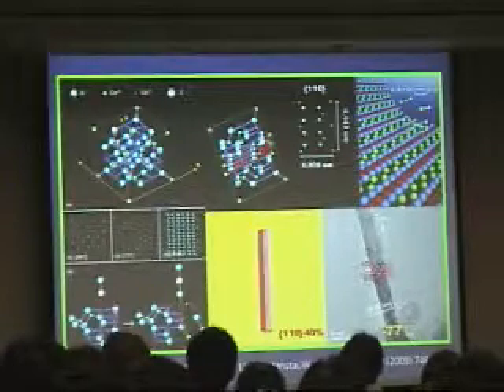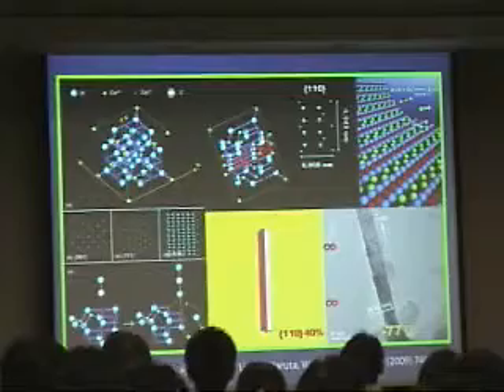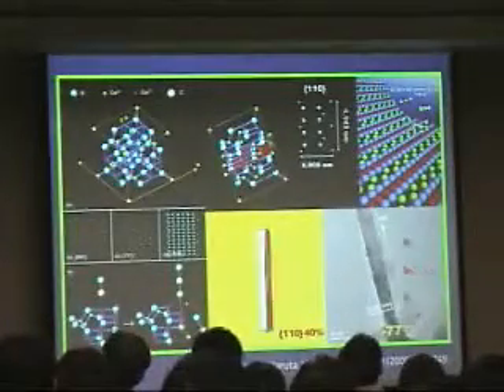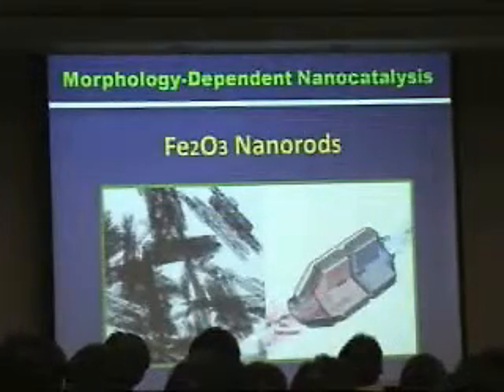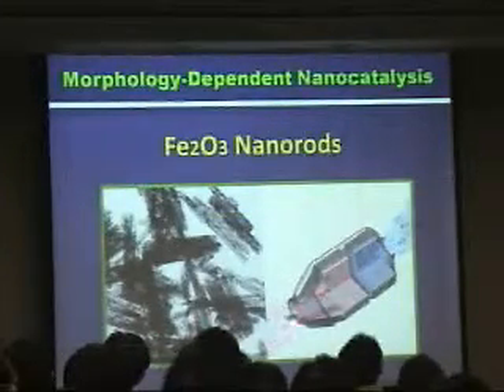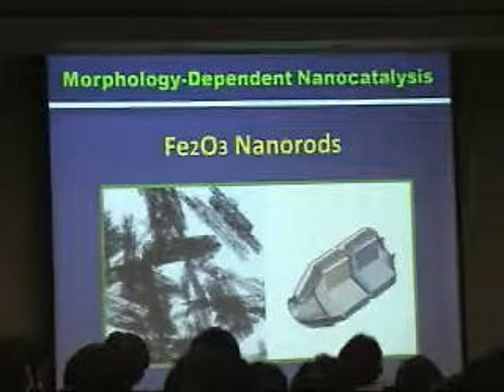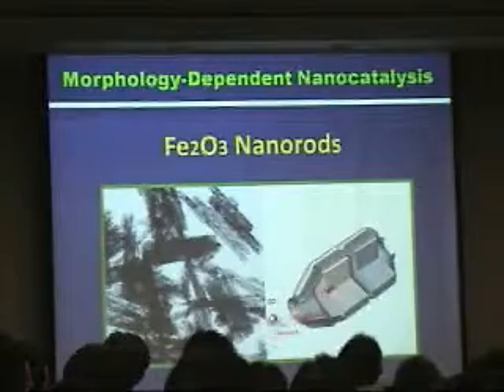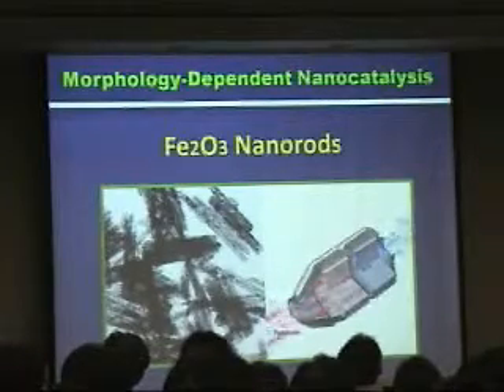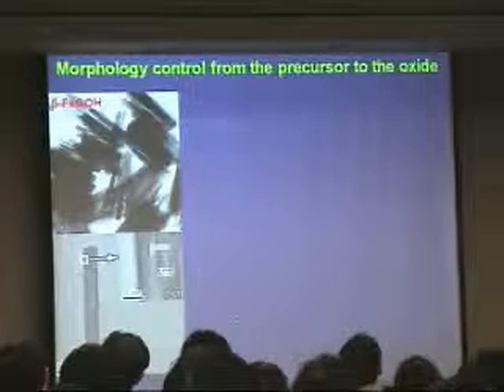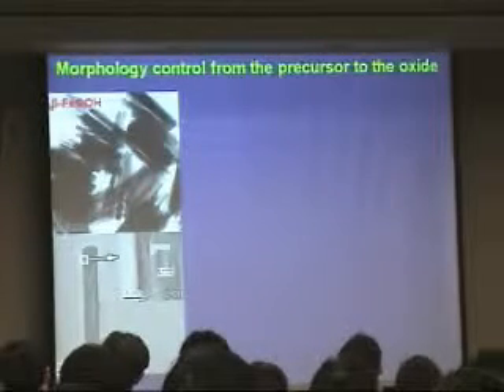So after this work, we also wanted to confirm the stability of this nanorod. We operated some other reaction at 500 degrees C. We still confirmed the stability of this nanorod and also the presence of the active site even after the reaction. Okay, so following this concept, we used another metal oxide, and we also got the same phenomena. That is the more common iron oxide nanorods. This oxide is very cheap and is also a very environmentally benign material. And we also started from the solution chemistry to control the shape of the precursor.